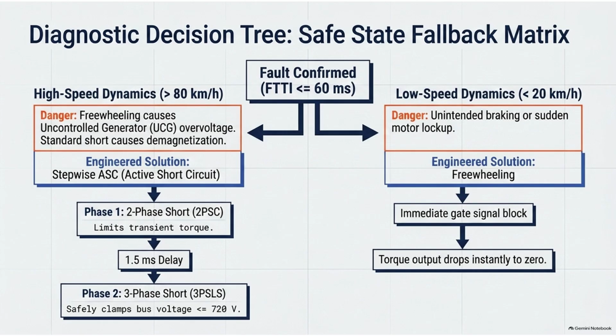Okay, so you have the motor howling at highway speeds, the short is detected, and the 60-millisecond clock is ticking. What is stage one? The moment the fault is confirmed, the system dynamically calculates the optimal switch combination and executes a two-phase short circuit, a 2PSC. Just two phases. Right, by only shorting two phases instead of three, it acts as a transitionary step. It suppresses the initial runaway voltage on the uncontrolled generation, but it doesn't create the massive sledgehammer effect of a full three-phase short. Then the system waits. It intentionally delays the next step for exactly 1.5 milliseconds.